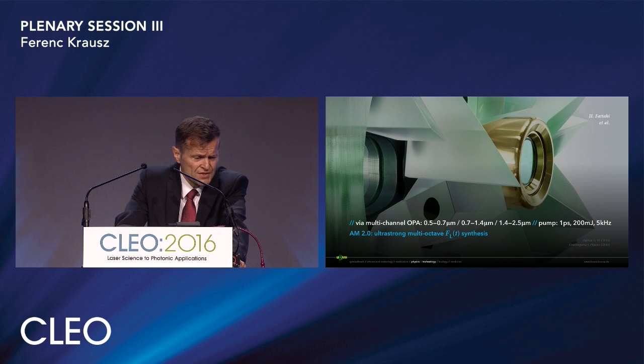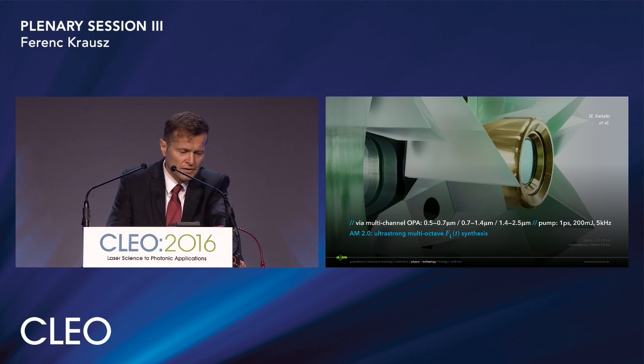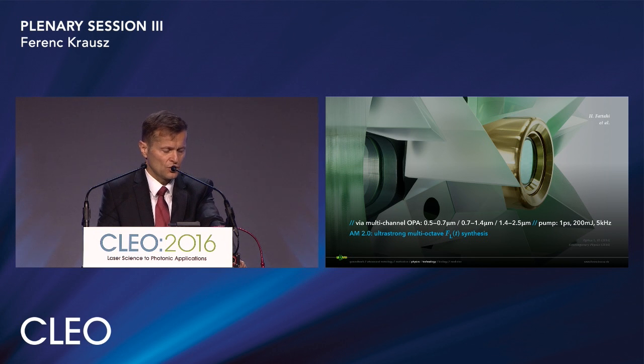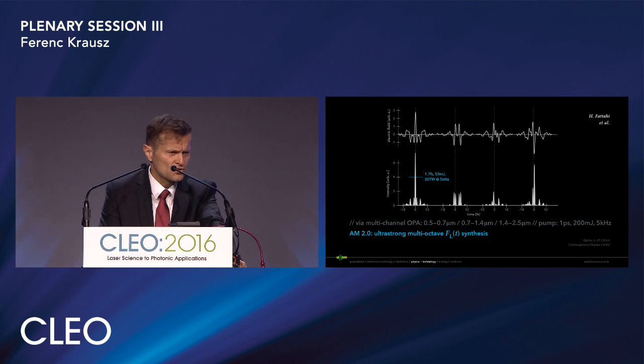Hanieh Fattahi and co-workers are now using a 1 kilowatt picosecond ytterbium YAG laser to pump broadband OPA channels in the visible, near-infrared, and mid-infrared, seed them simultaneously with one and the same phase-stable multi-octave continuum to allow coherent combination of their outputs to synthesize a wide range of ultra-strong multi-terawatt waveforms, including near 1 femtosecond 30 terawatt pulses at a 5 kilohertz repetition rate.